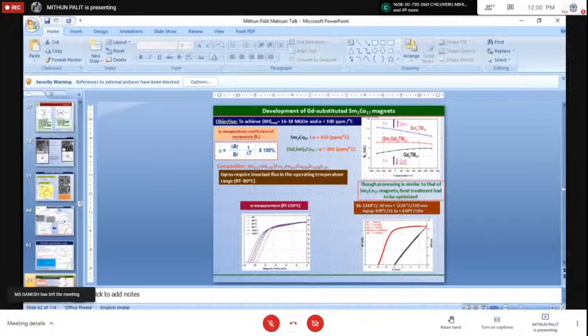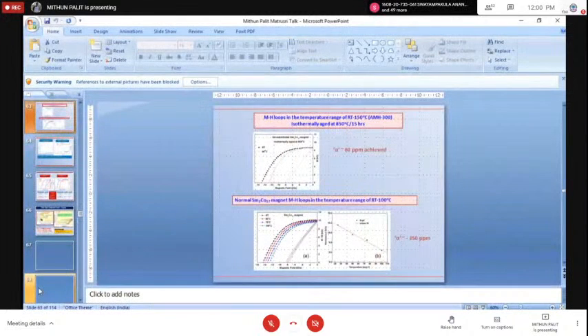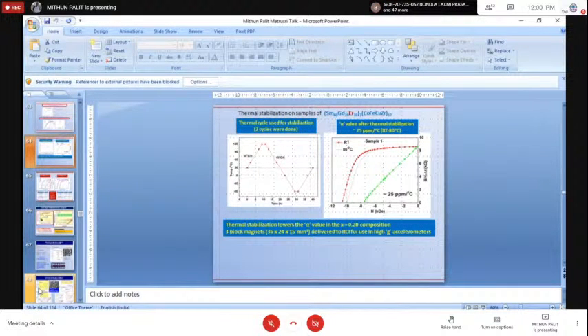However, we have taken our research further, and from this 60 ppm, what we can do is that we have also added some erbium along with gadolinium. Now this 60 ppm coefficient can be reduced to 25 ppm.